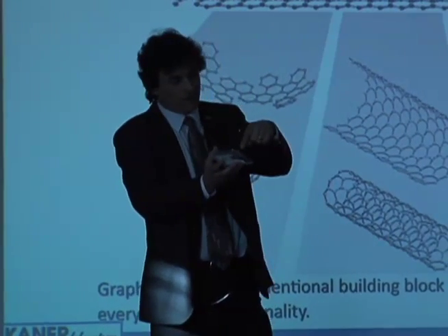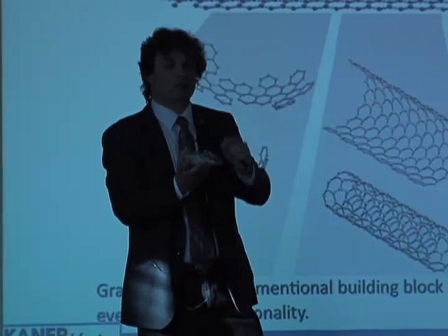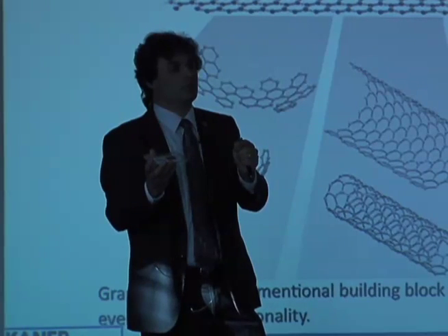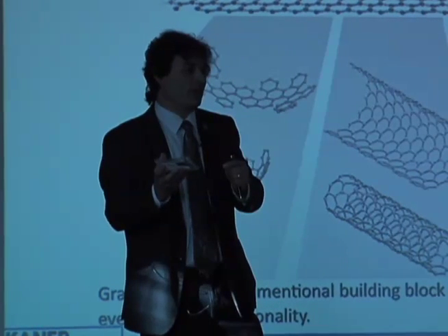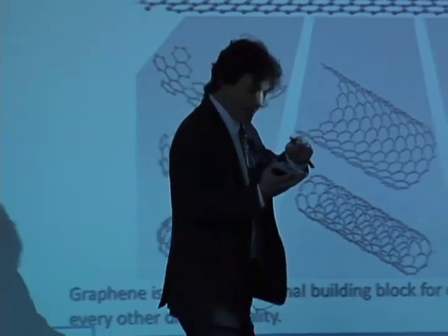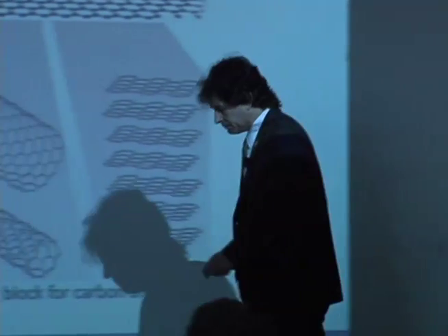After you identify that, if you look on the left, you'll see a piece of glass with about the same size rectangle of graphene. If you look through the edge, it's 100% relative transmission. If you look through the middle, it's 97.5%. Your eye should be good enough to tell the difference. Again, it's pretty much going to look like a shadow, but it's pretty amazing that you can actually see this with your eye.